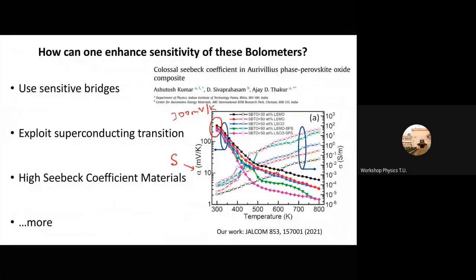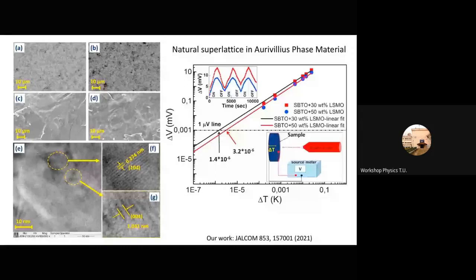And because this Seebeck coefficient is so high, as 300 microvolt per Kelvin, one can actually end up making a sensitive measurement of temperature changes and measure the corresponding voltage, right? So very small temperature changes like 10 raised to minus 7 Kelvin could be easily detected using conventional nanovoltmeters that we have in our laboratories. So therefore, this material had tremendous promise for bolometric application. So the reason why this material has a high Seebeck, let me just try to motivate.